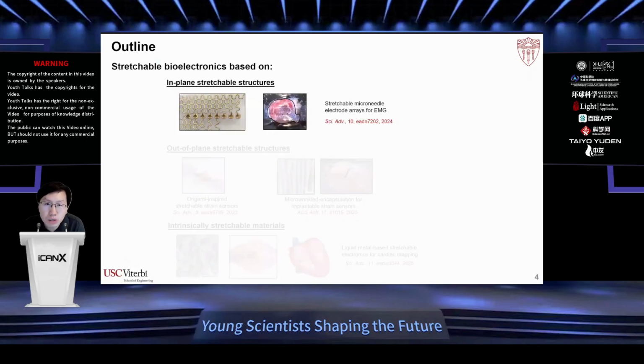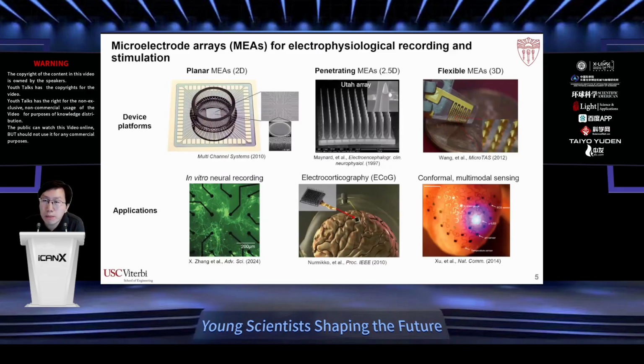The first example is how we use in-plane stretchable structures such as serpentine interconnects to develop stretchable microneedle electrode arrays for intramuscular EMG sensing. Microelectrode arrays, or MEAs, are a very commonly used technology platform for electrophysiological sensing and stimulation. We have 2D planar MEAs, and if you want to access the interior of tissues, we have 2.5D and 3D MEAs. 2.5D is on rigid electrodes, and if it's on a flexible substrate, for example a polymeric substrate, we can have flexible MEAs that can penetrate surface tissues.